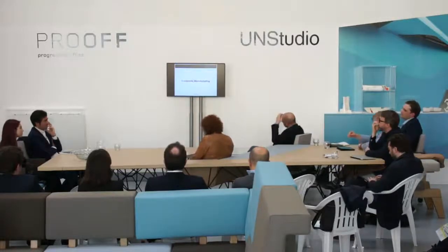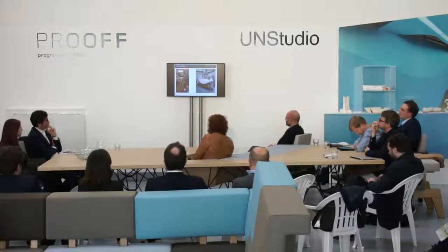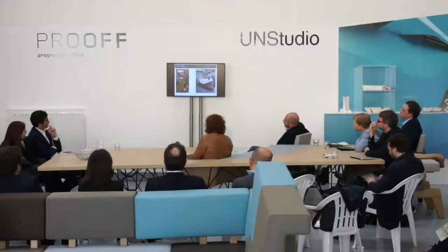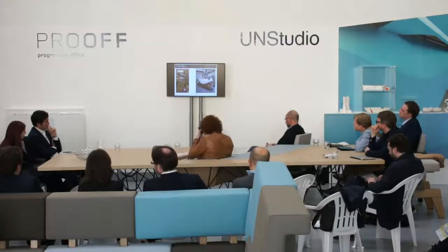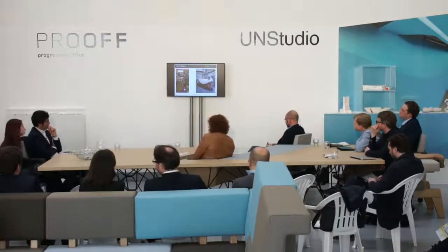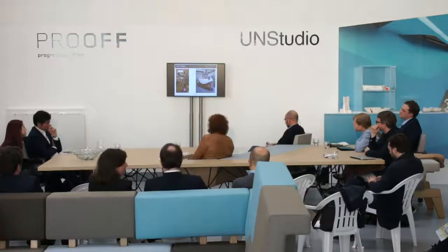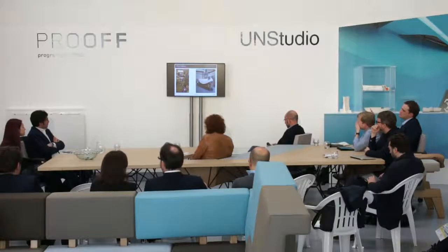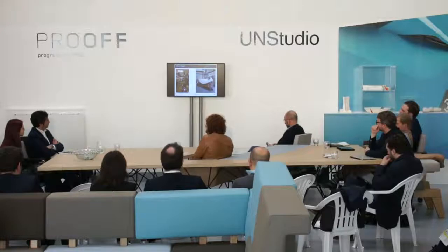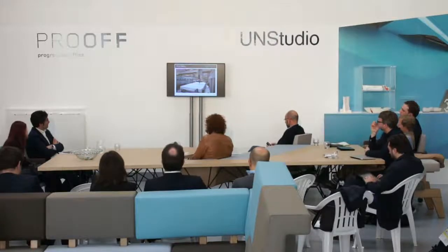I talk a little bit about the manufacturing process, which is quite important and uses actually most of the high-tech equipment. It starts off with the mold. Every composite element is molded, basically. Usually the molds are quite complex, biaxial curved. We are using 5- and 6-axis milling machines for very high accuracy and also to make sure that the design shape of the architect is fully taken one-to-one, basically.